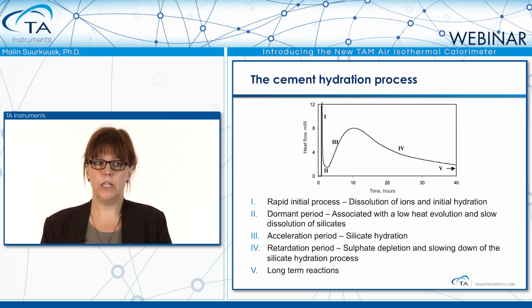Then the acceleration period starts, where the hydration process takes off, and that's called the main hydration peak. And then after that, we have the retardation period in number 4, where sulphate depletion occurs and the slowing down of the whole hydration process. And then there are long-term processes from after a day or two and up to weeks. You can follow long-term reactions in the cement or the concrete as well.